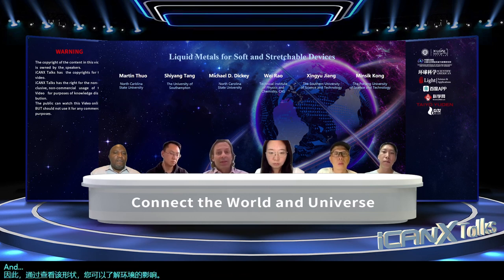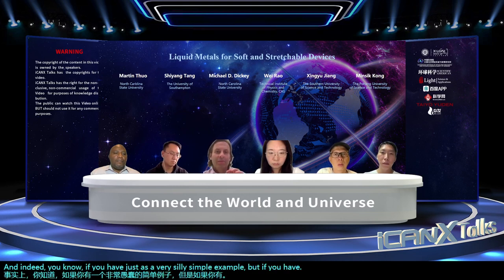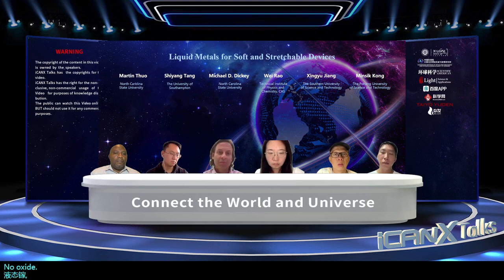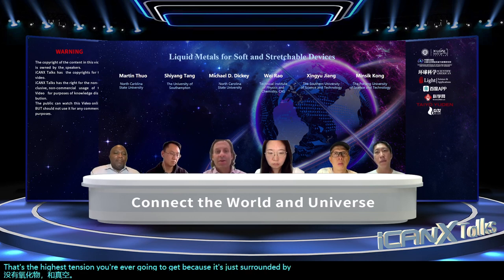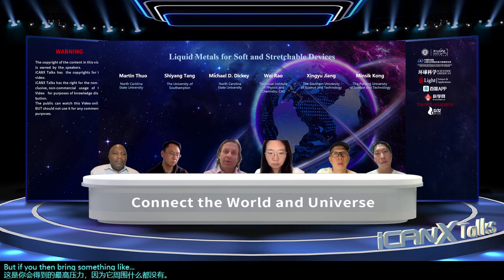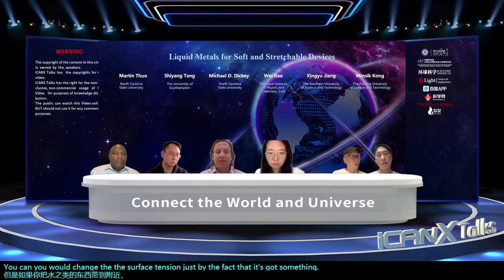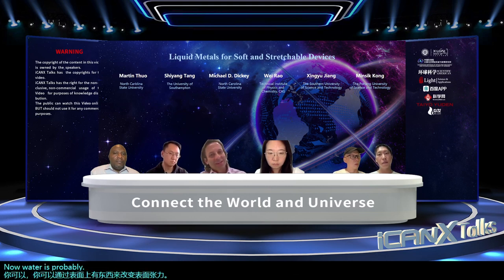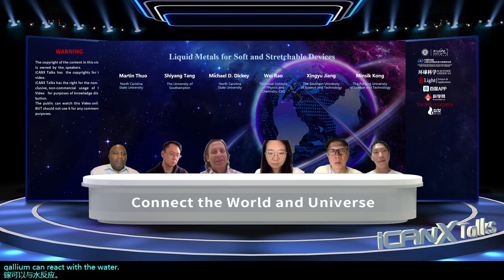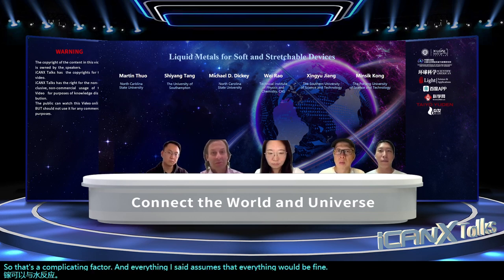And indeed, as a very simple example, if you have liquid gallium, no oxide, in vacuum, that's the highest tension you're ever going to get because it's just surrounded by nothing. But if you then bring something like water into proximity, you would change the surface tension just by the fact that it's got something butting up against the surface. Now, water is probably a bad example because, as I mentioned, gallium is reactive. Gallium can react with the water. So that's a complicating factor. And everything I said assumes that everything would be neutral, not reactive.